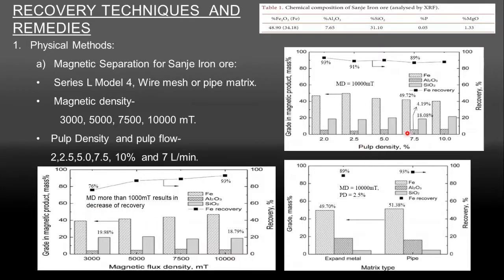And coming to pulp density, at constant magnetic flux density of 10,000 millitesla, from 2 to 2.5%, recovery has decreased from 93%, and if we keep on increasing the pulp density, there is constant recovery. Optimum recovery has been obtained at 7.5% pulp density, that is 89% of recovery. At this pulp density, the content of iron is 49.72% and alumina is 4.19% and silica is 18.08%.